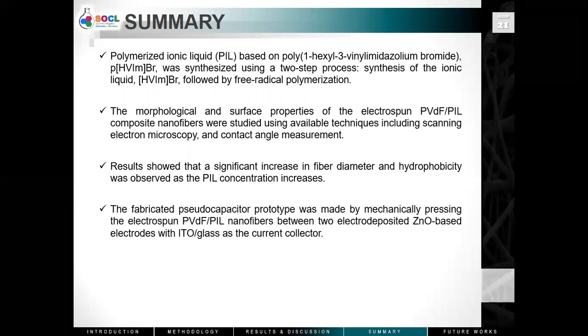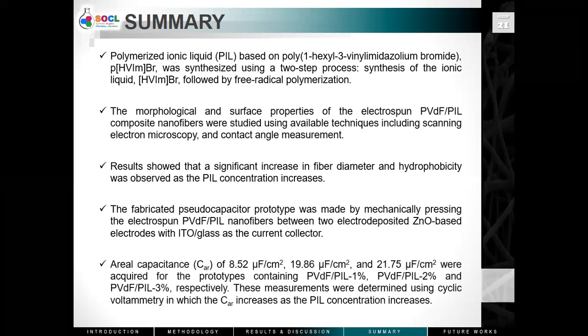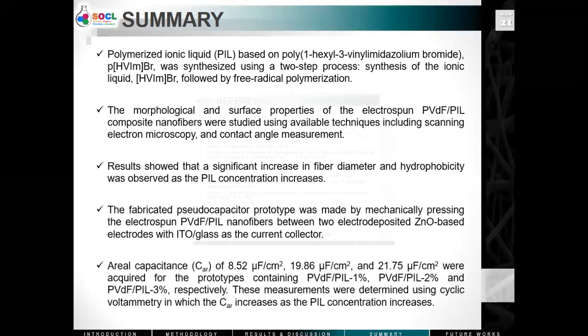The fabricated pseudocapacitor prototypes were made by mechanically pressing the electrospun composite nanofibers between two electrodeposited zinc oxide-based electrodes with ITO glass as a current collector. Areal capacitance values were acquired for the prototypes containing varied percent loading of the PIL. These measurements were determined using cyclic voltammetry, in which the areal capacitance values increase as the PIL concentration increases.